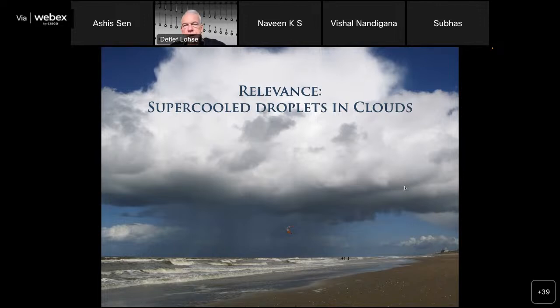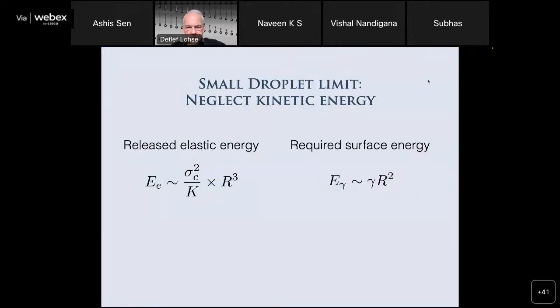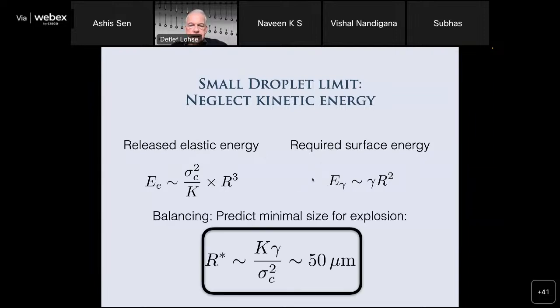And this was not understood up to now. Why is this happening so rapidly and so violently? And it could be that this process plays a role. So for this very small droplet, the required surface energy is, well, for the small droplets, you neglect kinetic energy, and then you balance the elastic energy with required surface energy, and then you can get the minimal size for the explosion. This is 50 micron.